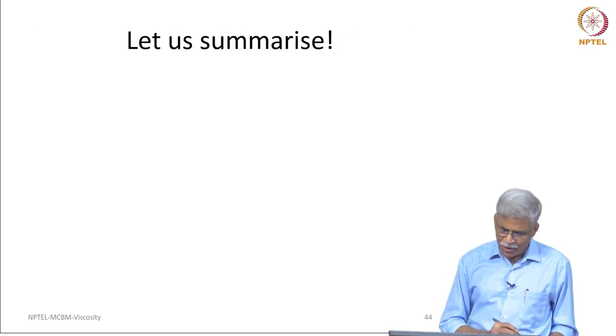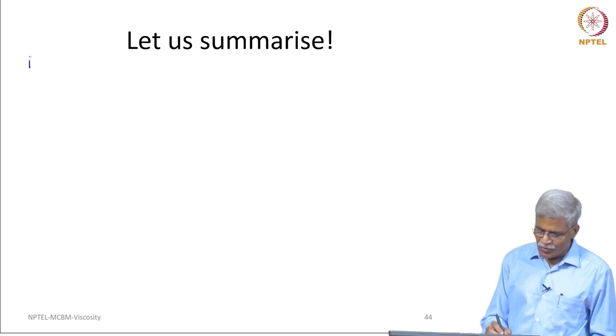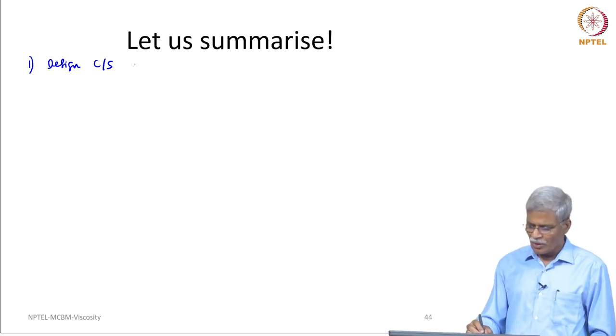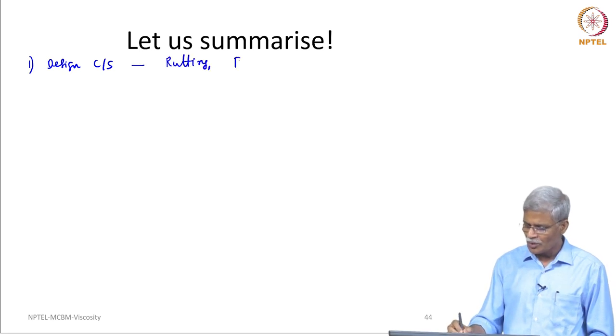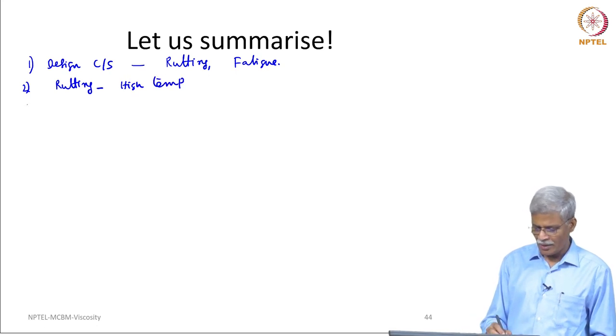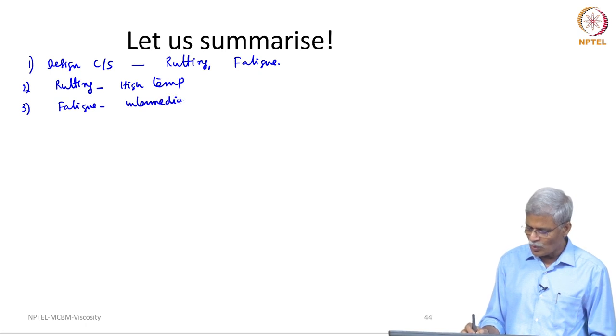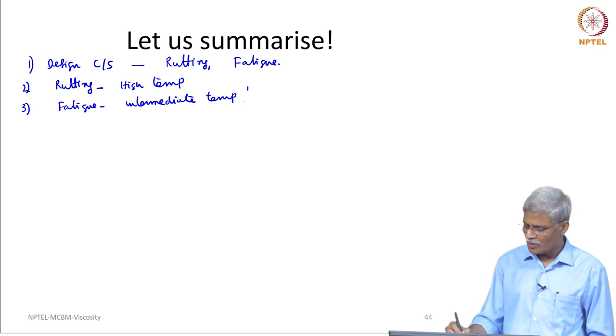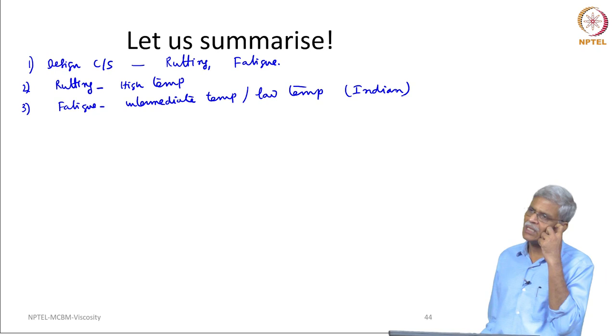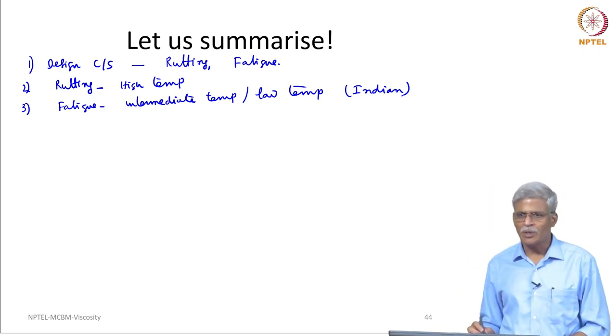So let us summarize what we discussed here. First, we talked about the pavement design cross-section, mentioning that the pavement has two bituminous layers, there is distress due to rutting, and there is also distress due to fatigue. Rutting happens at high temperature and fatigue happens at what I would call intermediate temperature — not necessarily low temperature by world terminology, but within the Indian context it is the low temperature because in most locations in this country, even at the lowest temperature, we are likely to have only fatigue damage and not low temperature cracking.